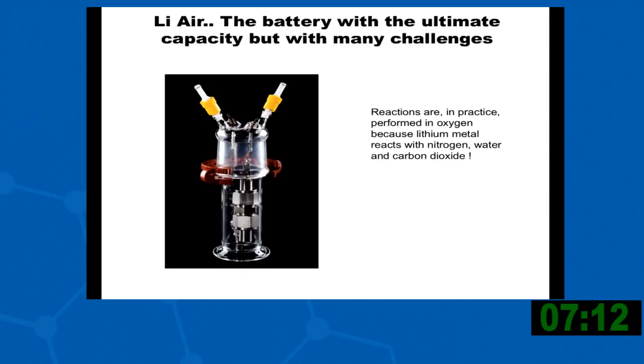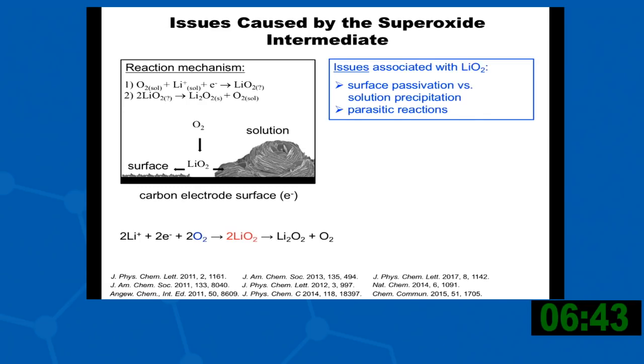So the other thing to point out, we always talk about a lithium-air battery, but in practice at the moment it's a lithium-oxygen battery, and that's because most of the other molecules in air, nitrogen, carbon dioxide, and water, all react with lithium metal. And so we perform all our reactions in closed systems where we only have oxygen. And it's incredibly irritating that even nitrogen reacts with lithium metal to form lithium nitrides.